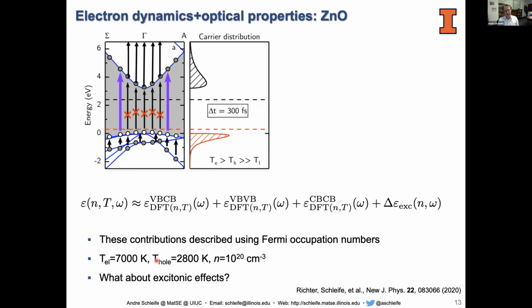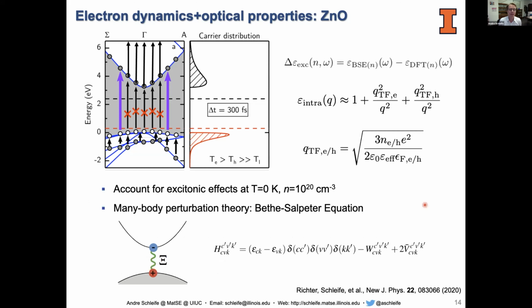Okay, now excitonic effects are important, and so what we did here is we simply accounted for excitonic effects at 0 Kelvin, again, because we currently cannot study temperature, but taking into account the free electron concentration in a similar way as we did for the doped material when I talked about methyl ammonium iodide. So we use a Thomas-Fermi model, we implement the extra screening, and then we solve the Bethe-Salpeter Hamiltonian.